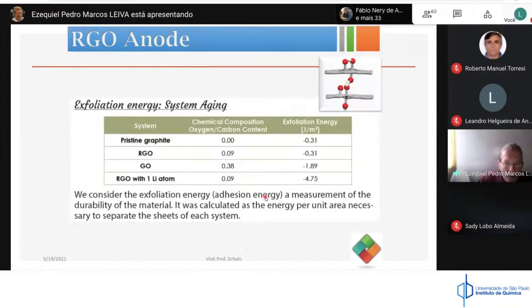Another thing that you can study is the exfoliation energy. You can see how difficult it is to split or to take away one layer from the other, and this gives you an idea of how stable your material is going to be. You can calculate the exfoliation energy in joules per square meter. This was for pristine graphite. This is for reduced graphite oxide, and this is for graphite oxide.